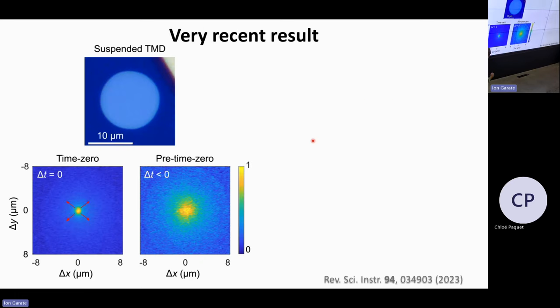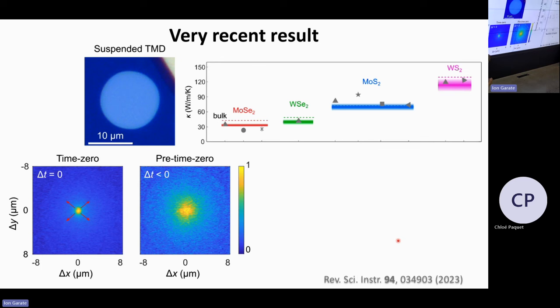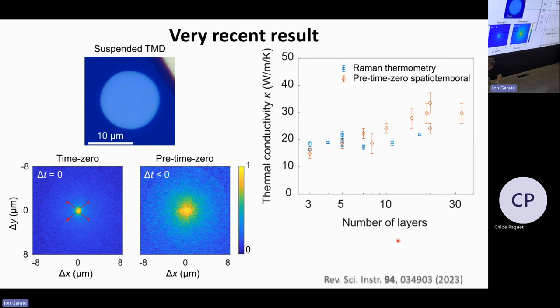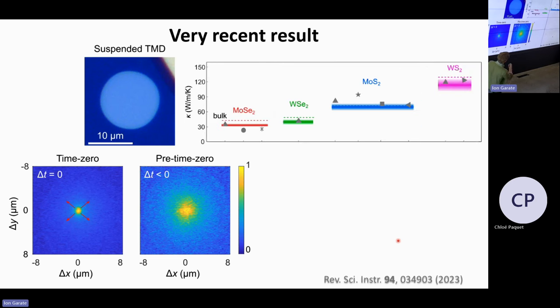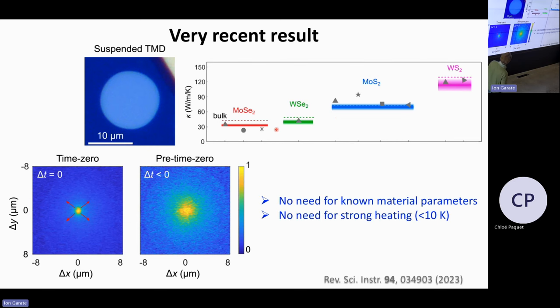I will probably skip this very recent work. This is just a technique we developed that we can use to look at heat transport. It's a pump probe technique. It was just published earlier this year in Review of Scientific Instruments. Let me just show that quickly because I'm quite proud of this. So we actually get very similar thermal conductivity as you get in Raman thermometry measurements, with the additional advantage that you don't need any material parameters. You just look at diffusion. So you just look at broadening as a function of time and then get a thermal diffusivity, which you can convert to a thermal conductivity. And the values we get match very well with values measured with other techniques for these four different TMDs.